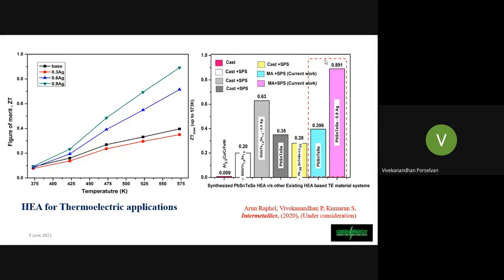Another thing is high entropy. So we know high entropy alloy is one of the fascinating alloys that are being used in structural applications. It is a multi-component alloy which has 4 or 5 elements in equal ratio. Okay, and this particular concept is being implemented in thermoelectric material. Thereby we can make a complex chemistry alloy that is made of different kinds of atoms, and reduce the thermal conductivity to the level of the ultrafine scale.